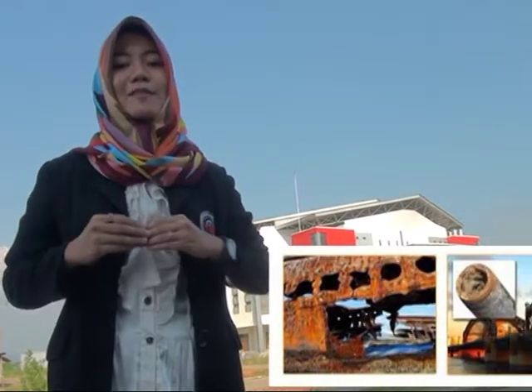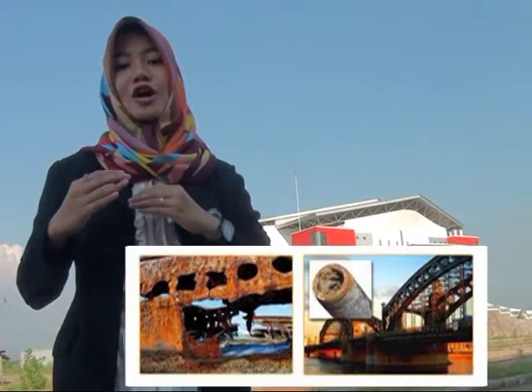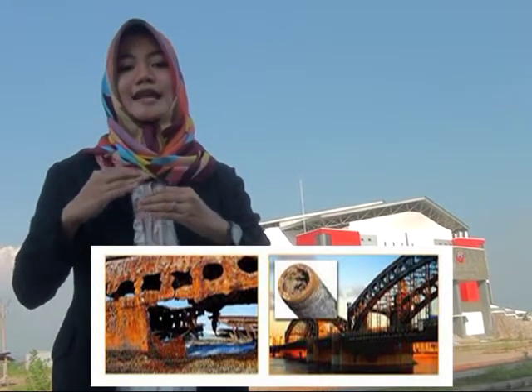Aloe vera can prevent the corrosion of stainless steel beverage cans. Inhibition efficiency and surface area coverage of aloe vera identified increases with the increasing concentration and the temperature. Aloe vera also inhibits corrosion at the varying temperatures. Adsorption studies show that aloe vera inhibits corrosion due to adsorption on the surface, reducing the corrosion rate